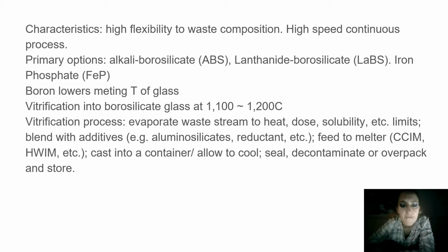Characteristics: high flexibility to waste composition, high speed continuous process. Primary options: alkali borosilicate, ABS, lanthanide borosilicate, LABS, iron phosphate, FEP. Boron lowers melting temperature of glass. Vitrification into borosilicate glass is at around 1100 to 1200 degrees Celsius.